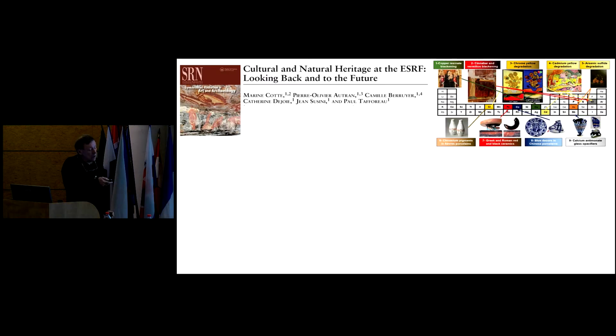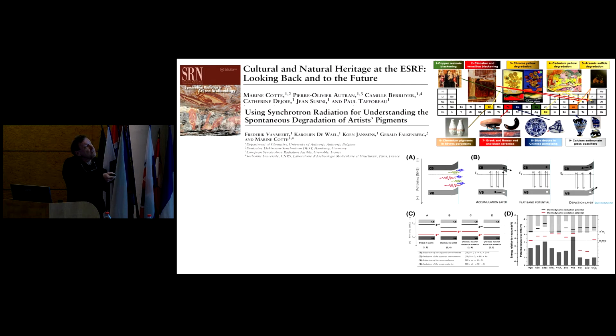What we also learned or noticed, if we go through this series of paintings and problems, is that most of the materials we were looking at, which show spontaneous discoloration, were semiconductors, and were therefore activated by light. And then we also learned that there are different subtypes of semiconductors, some of which push up the freed electrons or suck down the freed electrons, depending on how the conduction and the valence bands, the bound and the anti-bound states, are bent near the surface. And with that relatively simple picture, things also became more understandable. It was not just individual materials that did something. We could more or less start predicting when a particular reaction would happen.